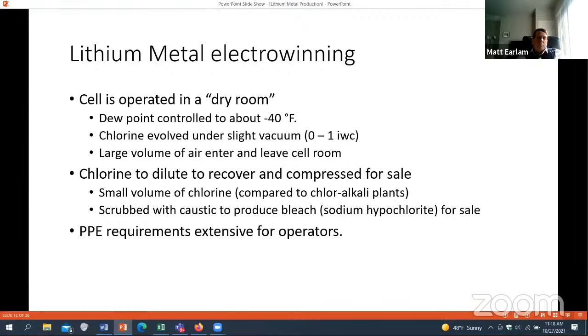And so unlike the magnesium process or the titanium process, where the chlorine is recycled to produce feed, in this process, since the brine is used and concentrated lithium chloride solids are used, there's no recycling of the chlorine, there's no value for it. Your electrolytic processes are in North America, your brine processes are in South America. So there's no connection between them in any way whatsoever, other than one's a customer of the other's product. And because of the chlorine gas and the temperatures involved, there's a lot of personal protective equipment that's necessary for the operators. Heat resistant material, respirators, things like that, that really add to the ergonomic burden of the operators when they actually do this job.